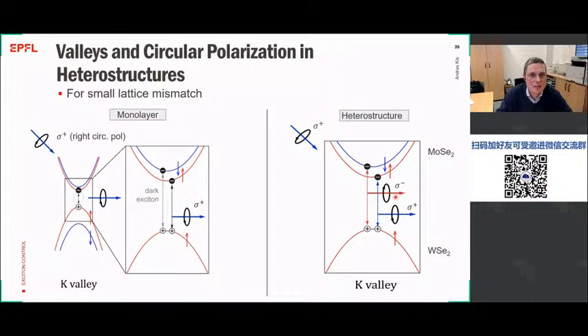So now what happens when you shine circularly polarized light on these heterostructures? In a monolayer, when you shine circularly polarized light on an isolated 2D material like tungsten disulfide, I said that the polarization of the light selects one or the other valley. And then you get the emission of light. If you have good polarization, you get the emission of light at the same polarization as the light that you use for excitation.